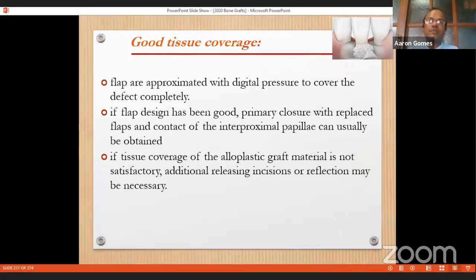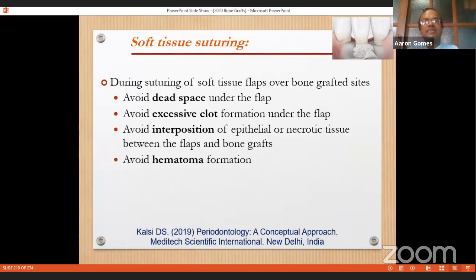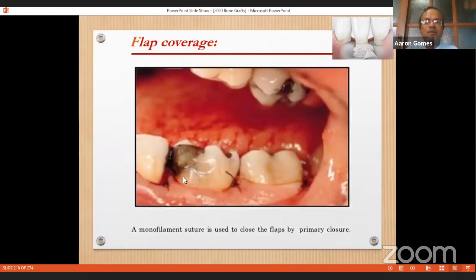The flaps are then approximated with digital pressure, and the tissue coverage of the material is checked. In case you're not getting tissue coverage, you can give, as I told you, those periosteal releasing incisions, or you can do a reflection deep into the vestibule. During the suturing, you should avoid dead space under the flap, avoid excessive clot formation, avoid interposition of the epithelium or necrotic tissue between the flap and the bone graft, and avoid hematoma formation. These avoids have been stressed in the textbook by Carranza in periodontology.